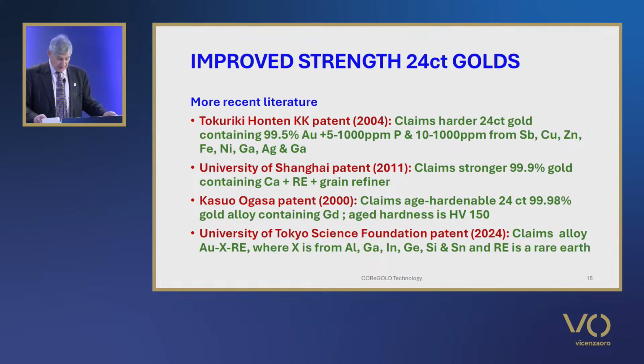A Chinese patent claims a stronger 99.9% gold microalloy containing calcium and a rare earth element plus a grain refiner, while a 2000 patent by Ogasa claims an age-hardenable 24-karat 99.98% gold microalloy containing gadolinium that reaches a hardness of about 150 Vickers after aging.